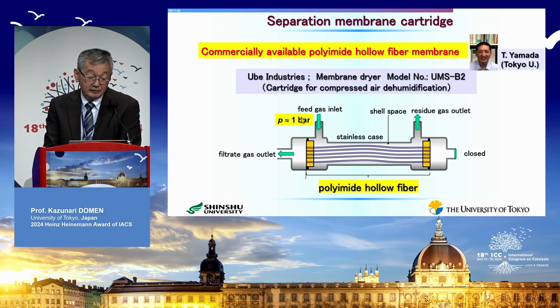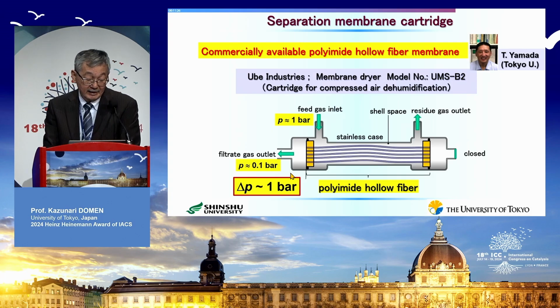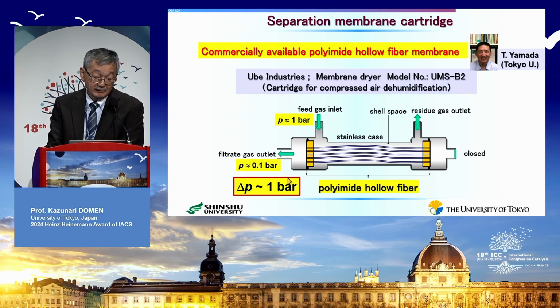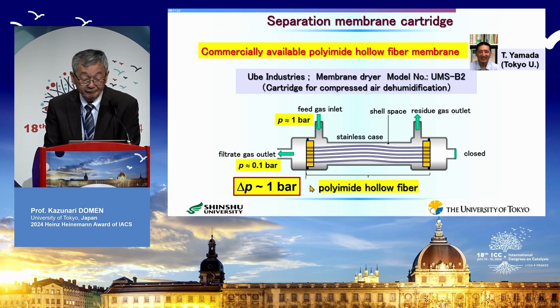At first, we introduce 1 bar of hydrogen, oxygen, and water vapor mixture from here, then it goes through this one and goes outside here. And this side is evacuated to about 0.1 bar. Therefore, the pressure difference between outside and inside of this hollow fiber membrane is less than 1 bar. So we don't need to use so much energy to separate hydrogen.